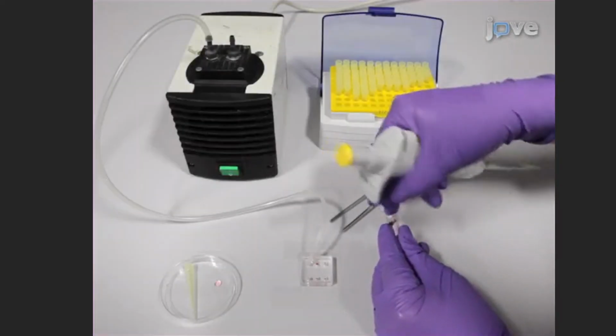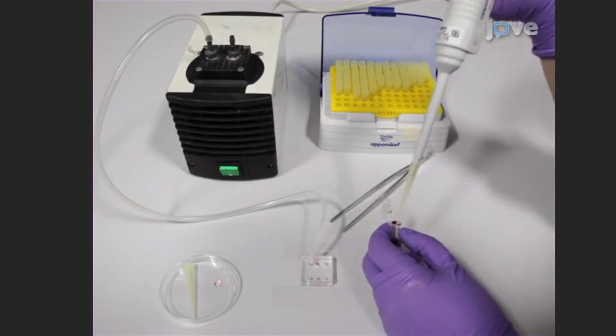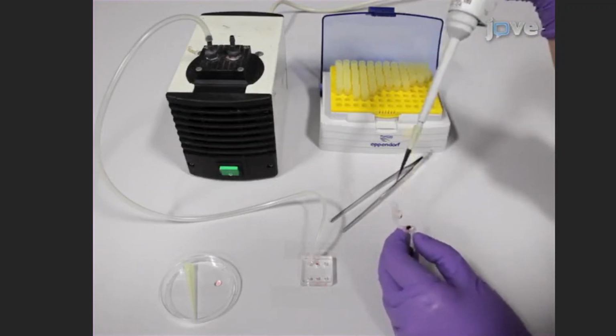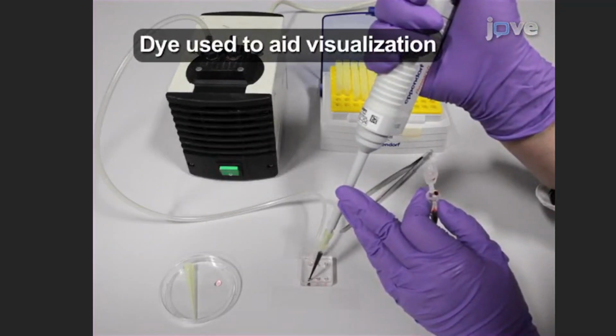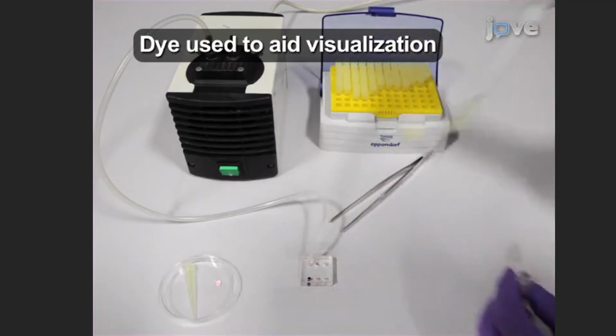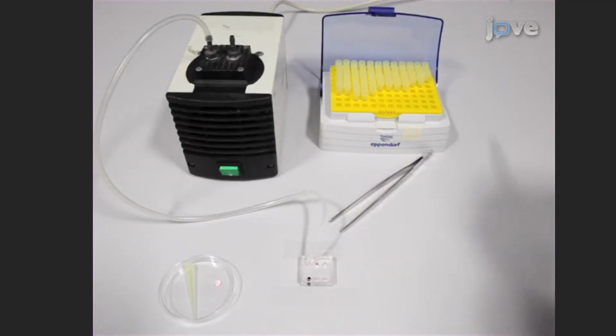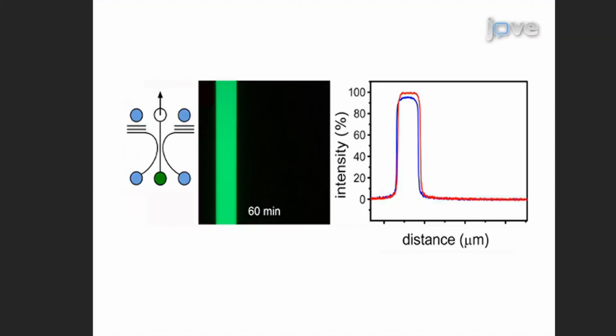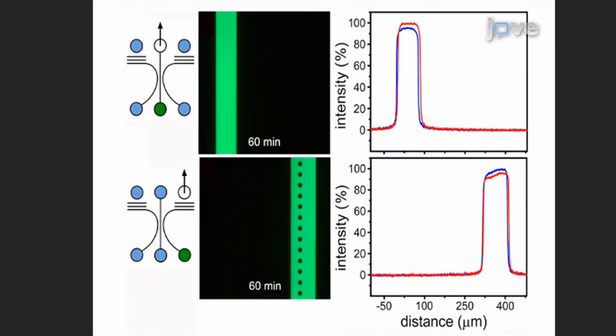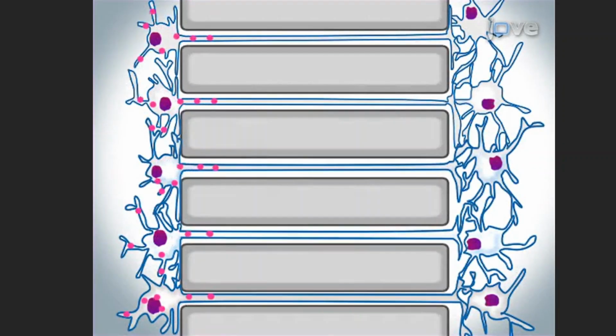To selectively treat either neuron culture compartment or the central neurite outgrowth compartment, dispense 20 microliters of the test substance into the bottom port connected to the channel of interest and aspirate from the port directly above. In this example, a selective treatment has been applied to the central compartment, and in this example, the flanking compartment has been treated. Treatments were established in 1 minute and were maintained for 60 minutes. The neuron co-cultures can then be monitored to measure the propagation of materials or pathology.